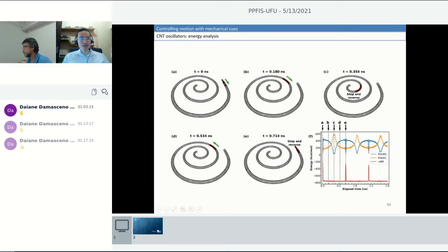What I can also say is that there are papers on nano-oscillators. They're different. In the other papers, they just have this open end with a tube leaving, and it goes straight through the tube and moves outside of another open end. In this kind of configuration, they also see the effect of chirality. They see that if you have, for example, an armchair inner tube and an armchair outer tube, the motion stops more quickly.